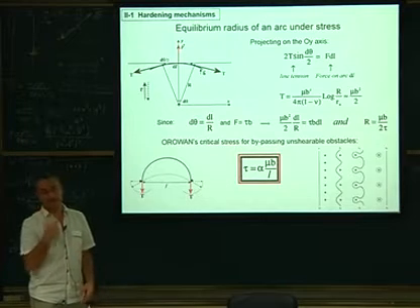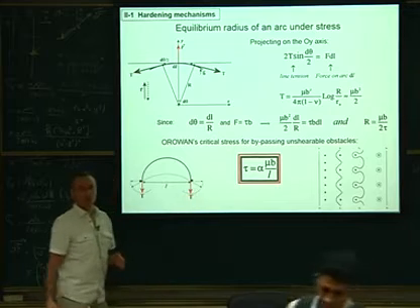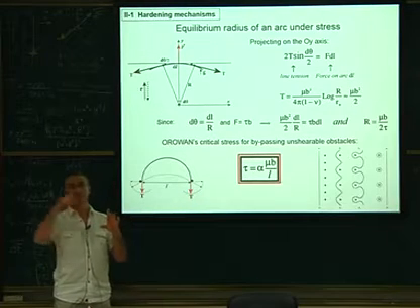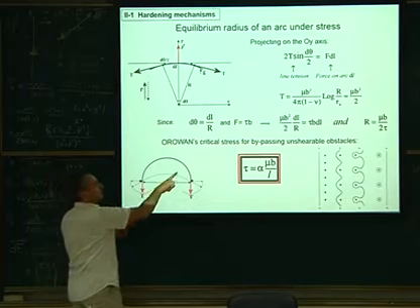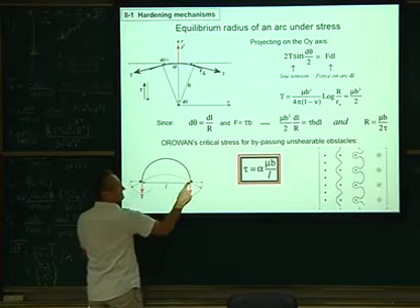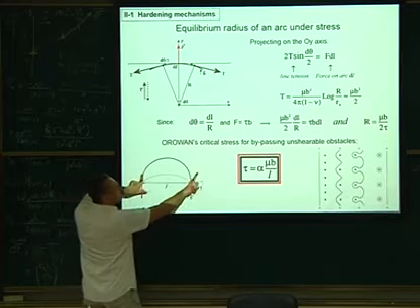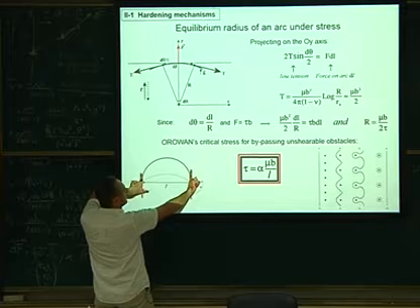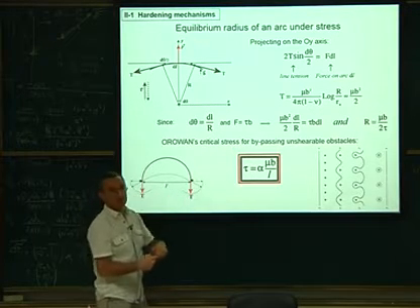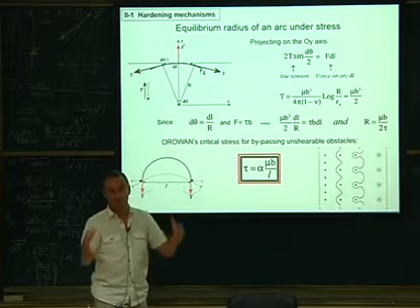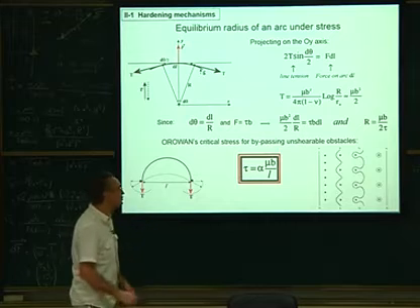And you can actually analytically see that because in practice the dislocation is not a circle. The dislocation is an ellipse. I showed you that yesterday. Because of the line energy, it is more like an ellipsoid, elongated toward the Burgers vector. So if you have the Burgers vector that way, you will have something like this. But it will still be unstable, and when is it unstable? When those two derivatives will be parallel. So if you take those two derivatives here, when the two are parallel, it could be inclined. When they are parallel, the dislocation is unstable, so you reach the critical stress, the maximum stress to blow out your first dislocation, to create your first loop.